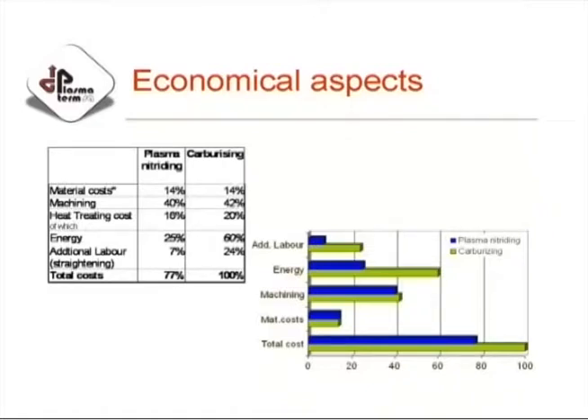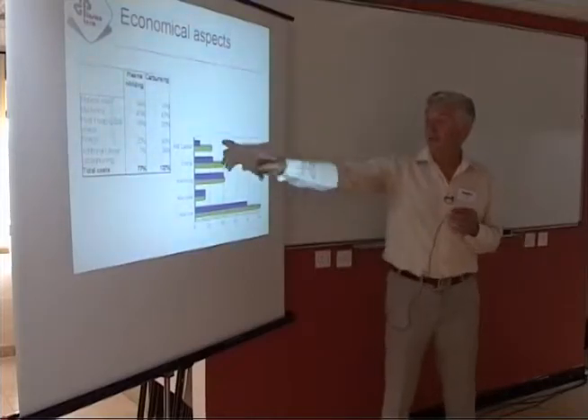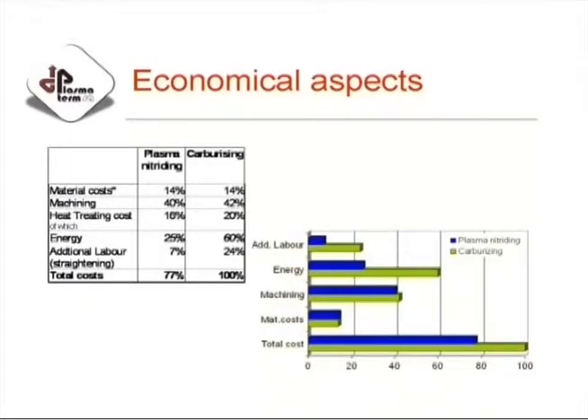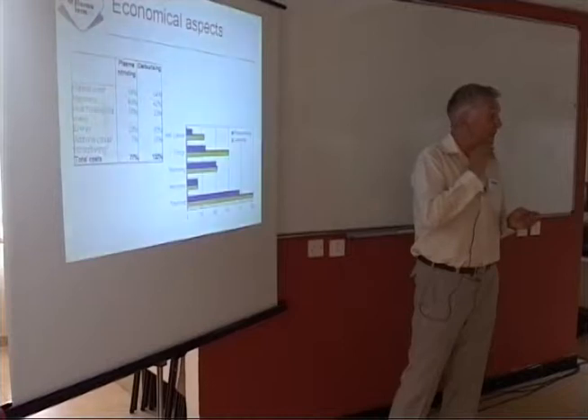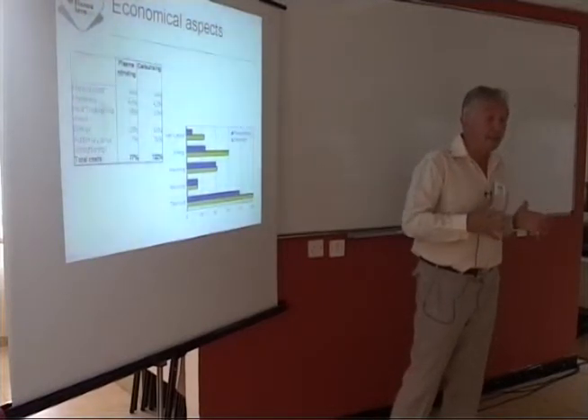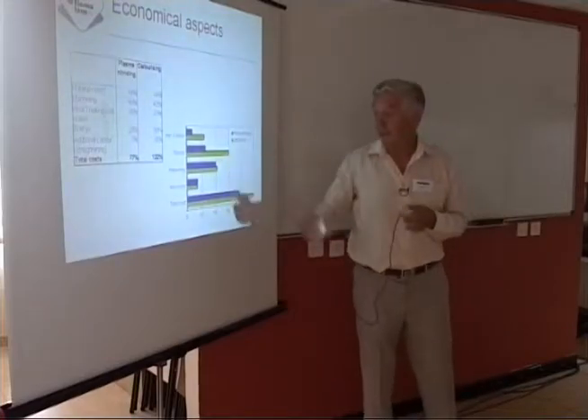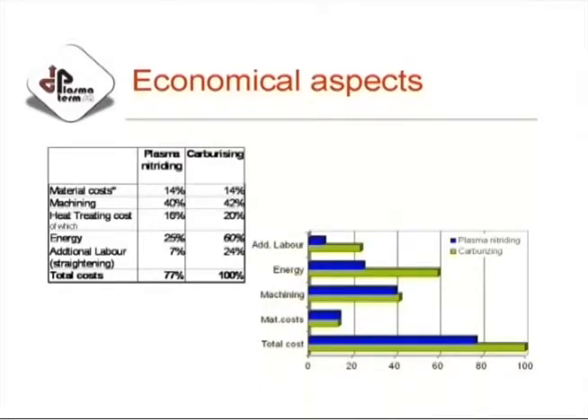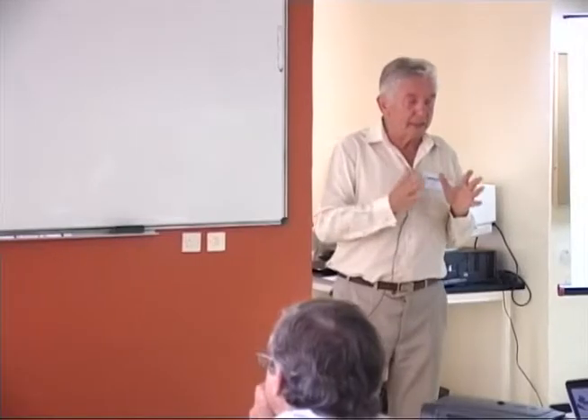So I just try to show which are the differences. The additional labor for post-machining and such kind of thing, especially for straightening, is much smaller for plasma nitriding or nitrocarburizing than for carburizing. The same for the energy use. Certainly the energy is lower, and especially as the heating is just for the parts, and we do not heat the furnace, the specific energy needs are much less. Machining costs are less. The material cost is the same. We use the same material. And you see the total cost is more than 20% less for a plasma nitrided or plasma nitrocarburized component than for a carburized component, which is a big difference.